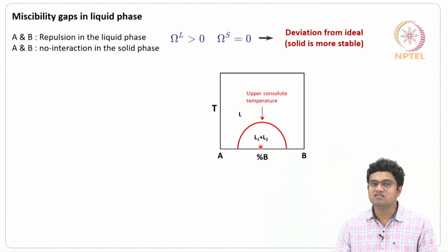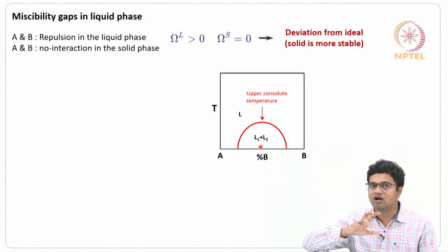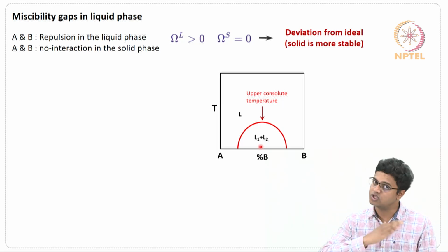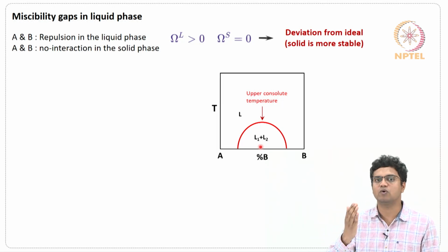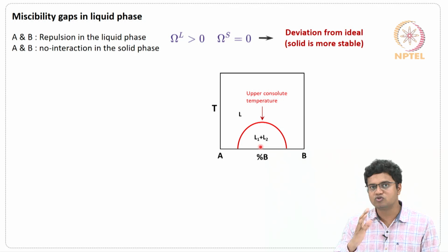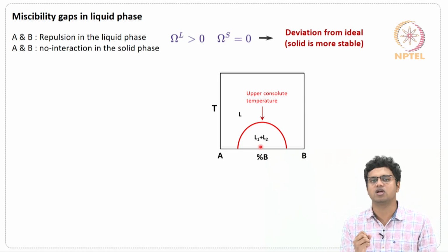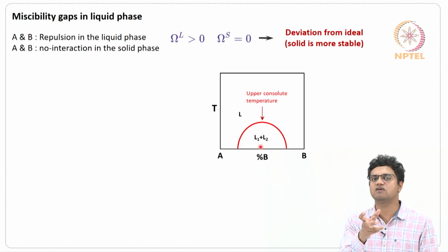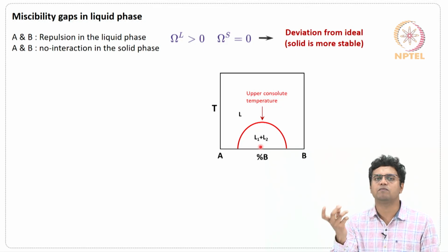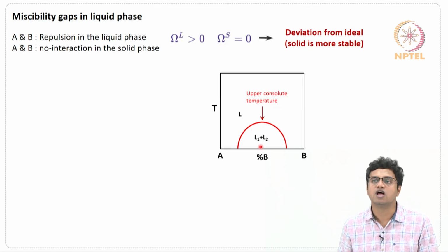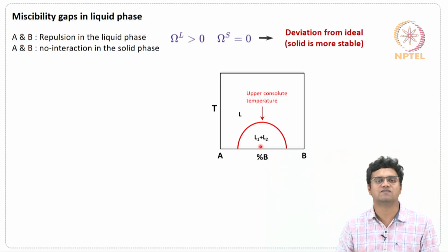Since their chemical composition is different, though they are chemically homogeneous, both constituting A and B only, due to the compositional variation there exists a physical boundary. So that's how they can be physically distinguished. And since they are physically distinguishable, they have a boundary, they can be mechanically separable as well. So that's the reason L1 and L2 are now ascribed as different phases.